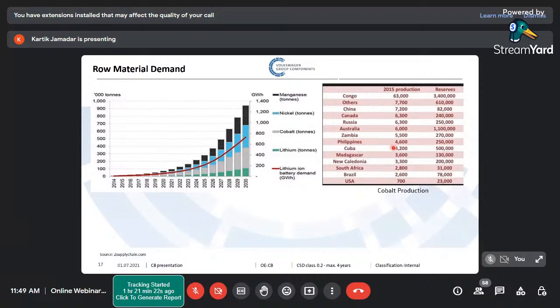And we have a big problem: there is not enough raw material available. Cobalt is coming mainly from the Congo. They have 3.4 million tons of reserves, but our production is at 63,000. They expect that in the next 10 years the cobalt mines will be empty. The copper mines will be empty in 50 years, and lithium would not be available for more than 30 years. So we have to find some alternatives, and the alternative is the recycling process.